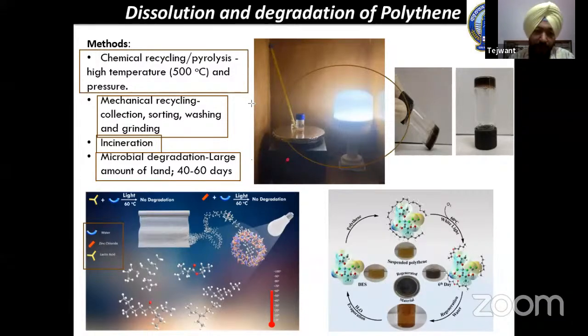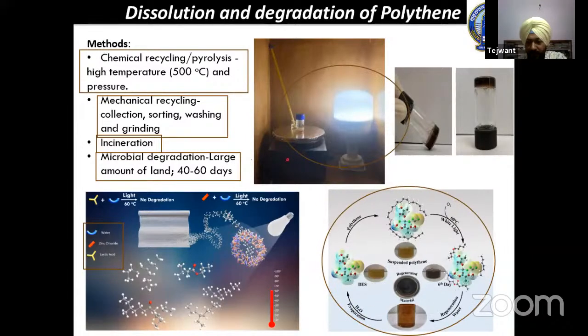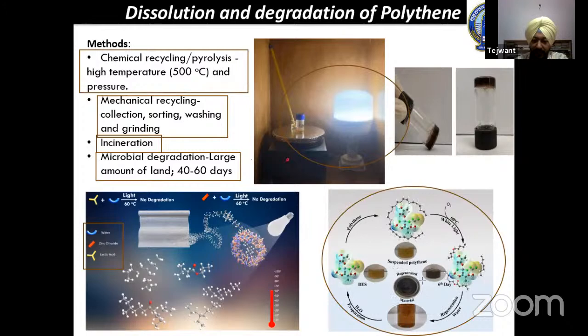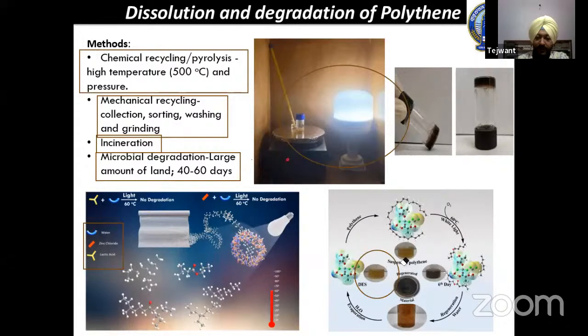So what we have done is dissolve the polymer and then precipitate out the dissolved material. Here we can see, in the last column, the dissolved material has been regenerated by using water as an anti-solvent. The regenerated material has been characterized. It has been found that the regenerated material has a much lower molecular weight compared to that of the polyethylene. The presence of ester as well as carboxylic functional groups and other polar groups has been established by a variety of techniques on the regenerated products. The presence of such polar groups makes the regenerated product soluble in some polar solvents such as methanol, acetone, etc. After regeneration of this material, we evaporated the water and were left with the solvent again, which has been recycled for the dissolution of polyethylene again.